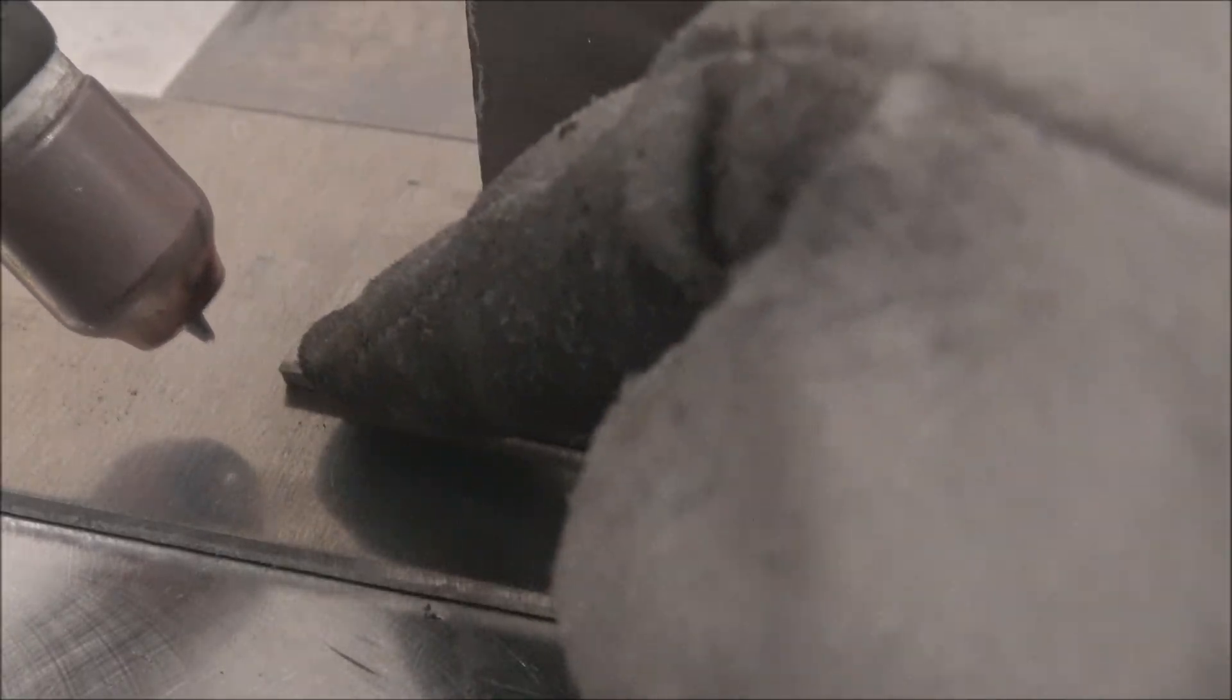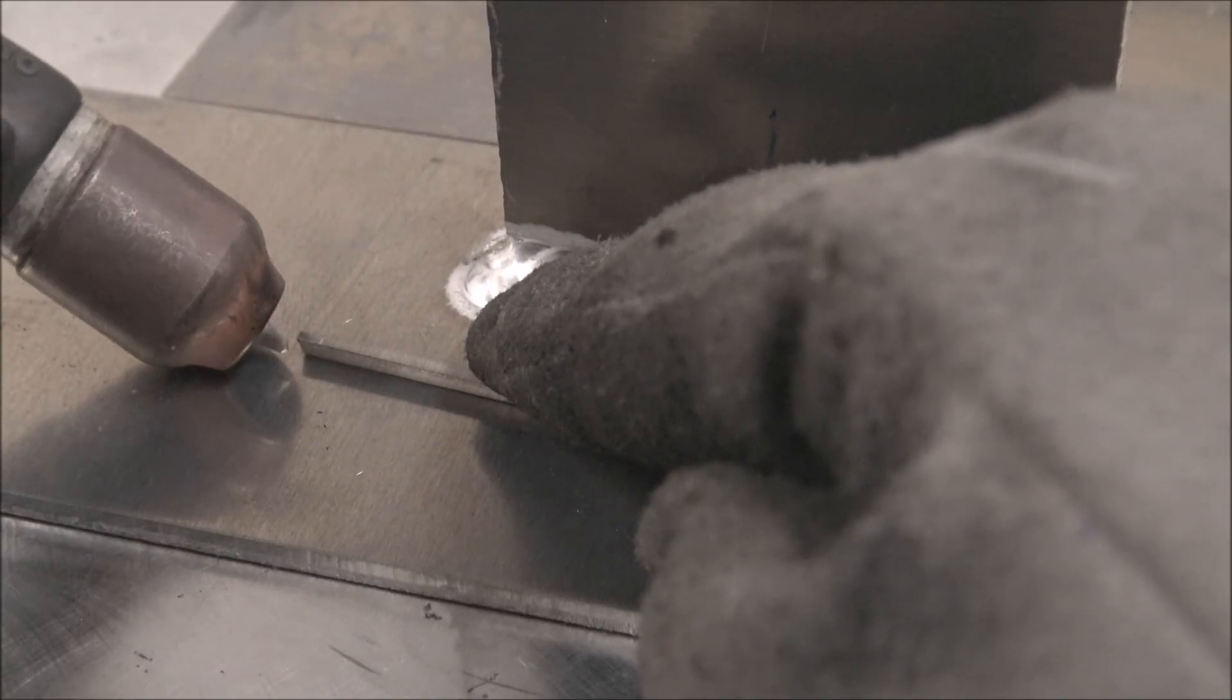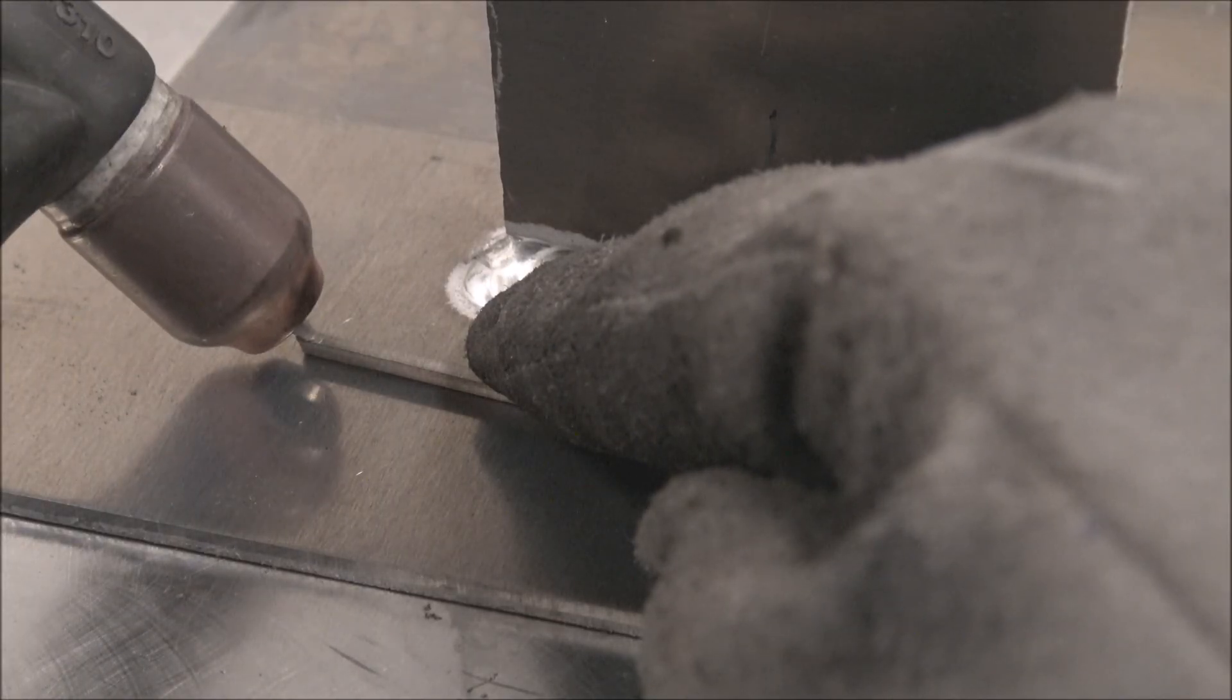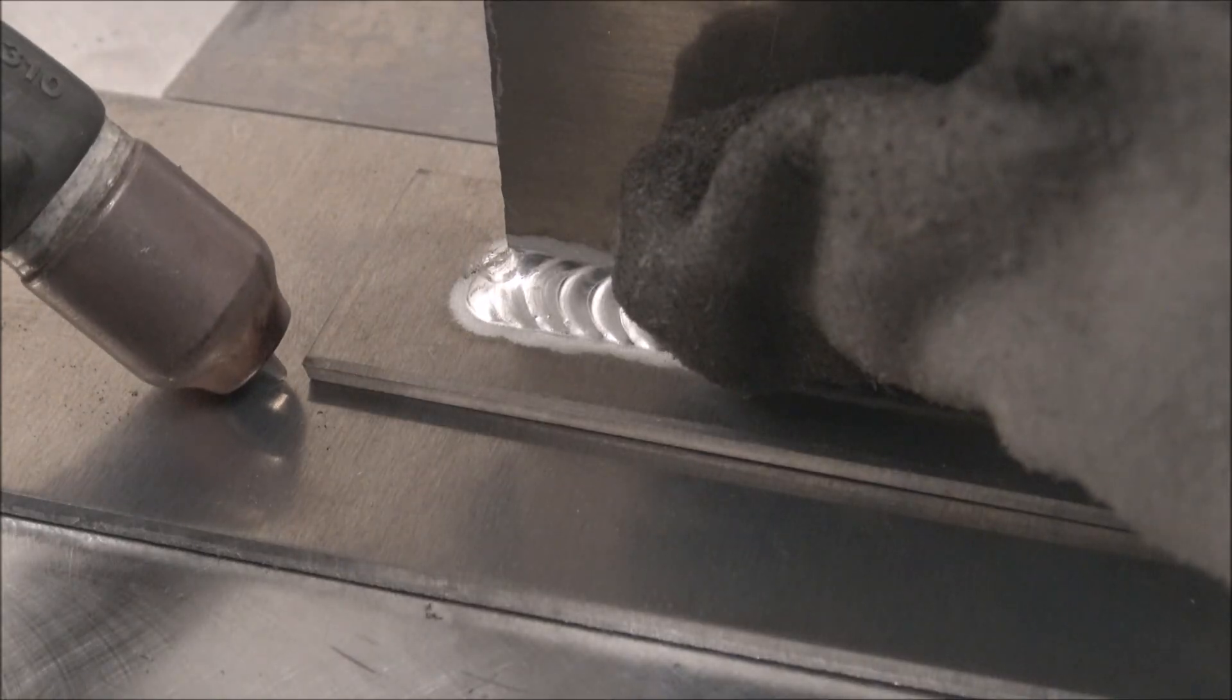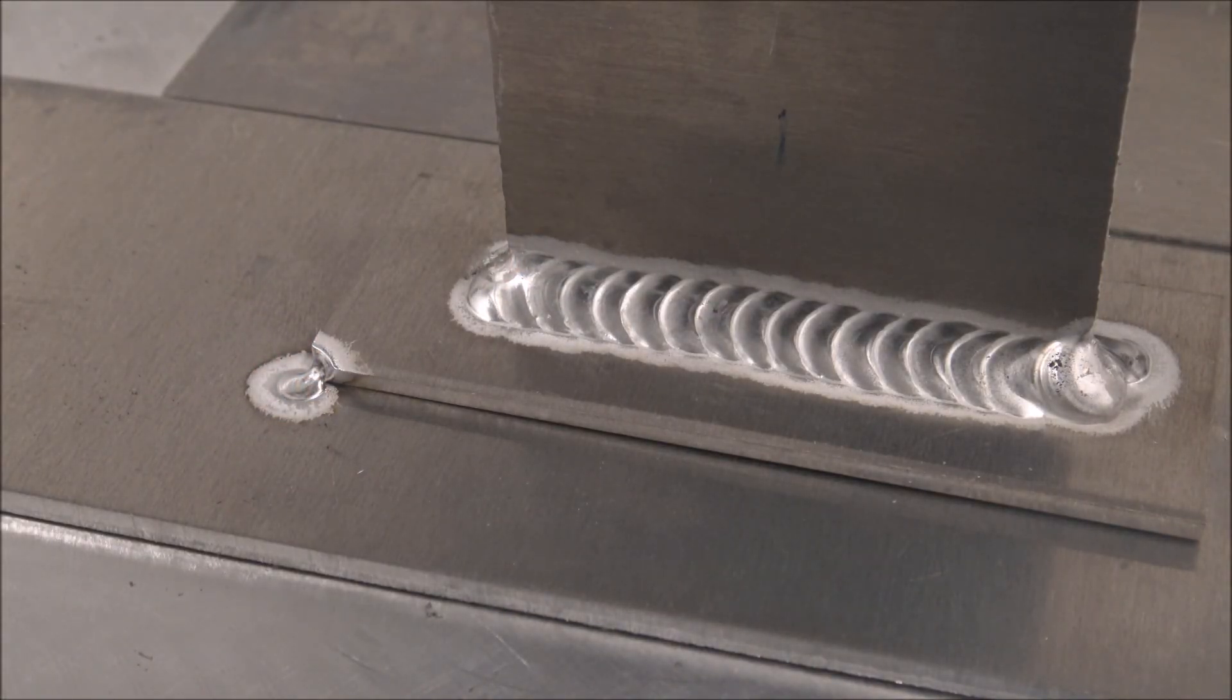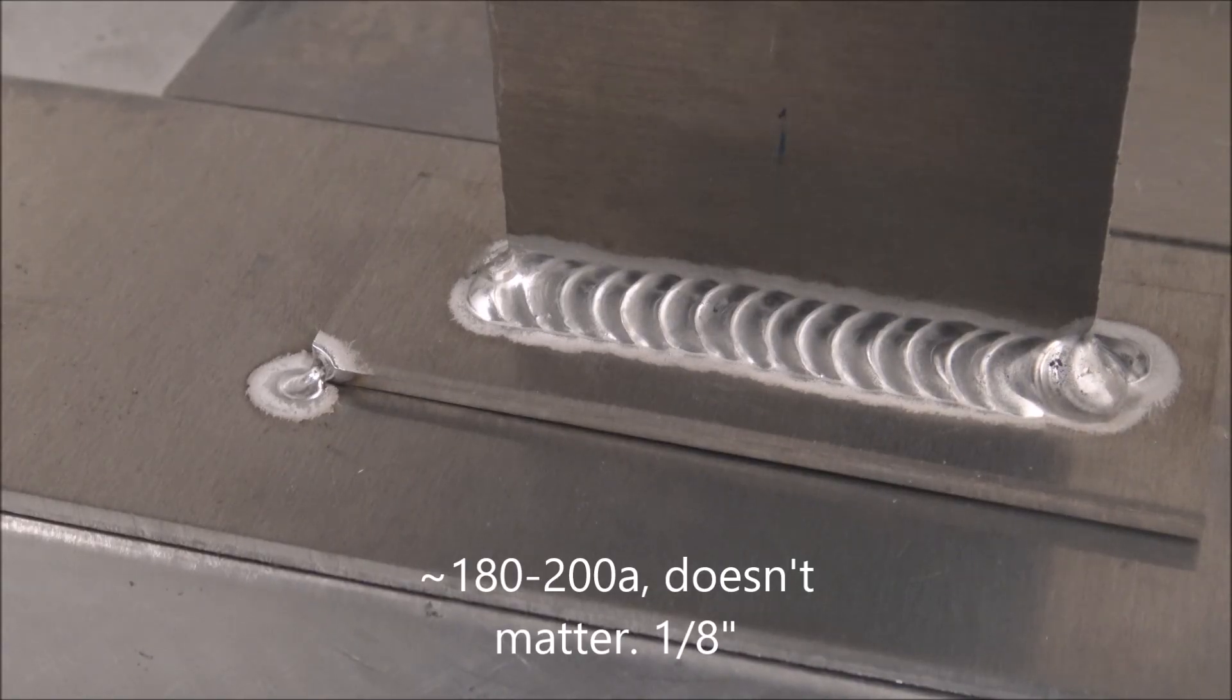All I focus on is making sure my parts are touching good and then I just get it. Like parts like this, you can rest your cup to get it super stable. Get it right in here. Point it exactly where you need between both parts. A little bit more heat down to the bottom because it's thicker and it's not going to burn away like this little corner will. Then just get into your heat as quick as possible. Don't pussyfoot around about it. Just get right after it. See how easy and quick that was? The part was touching and I have the welder set at 183 amps. All I did was just floor the pedal and it fused right together.